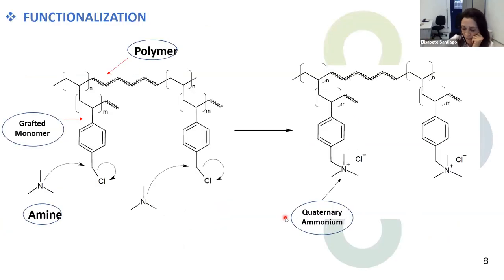So the functionalization is based on introducing functional groups on these side chains. The grafting promotes the introduction of side chains, and the functionalization promotes the amination, I mean the formation of functional groups. The functional group used in AEM is quaternary ammonium. That is promoted by amination reactions, using tertiary amines to produce this functional group.